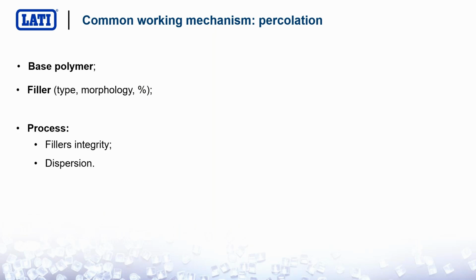What is the working mechanism of these fillers? It is called percolation. Percolation is a threshold between a non-conductive situation and a perfectly conductive situation. It means that from some value of contact between conductive fillers on, you will have proper electrical conductivity. So percolation is achieved by carefully selecting the base polymer, especially the viscosity of the base polymer, the kind of filler, the type, morphology, and content, and the right process. So you have to process them correctly in order to achieve a perfect dispersion without breaking, without destroying the fillers.